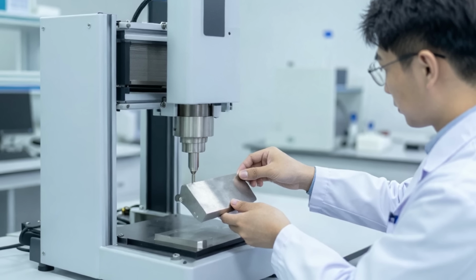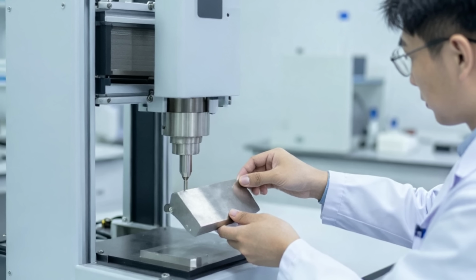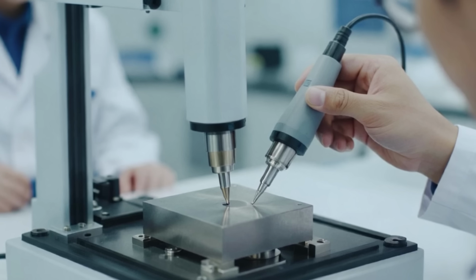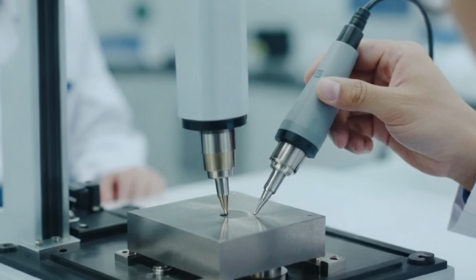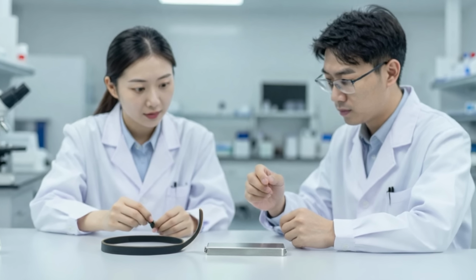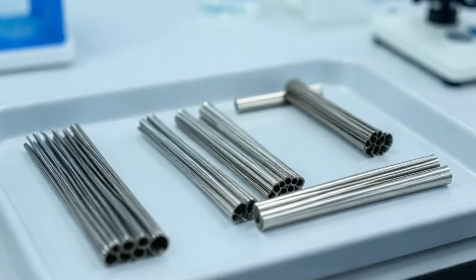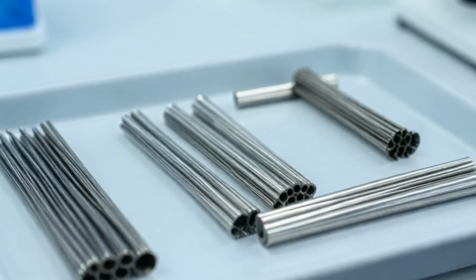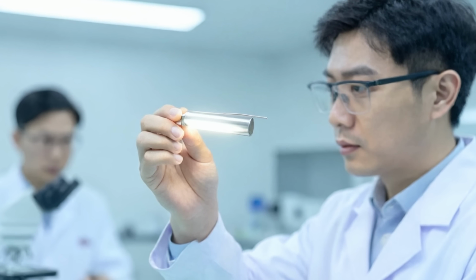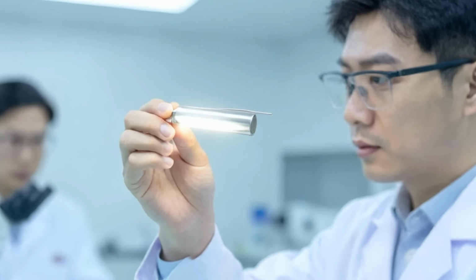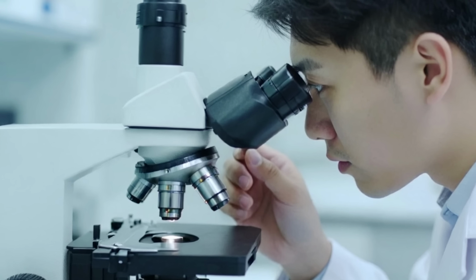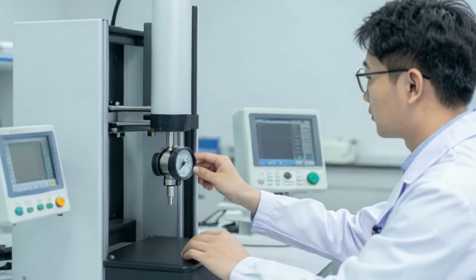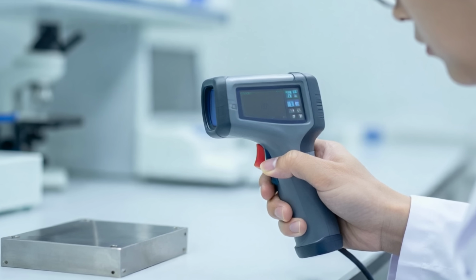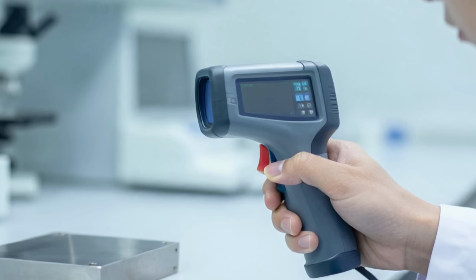Certain materials, when you mechanically stress them, release heat, and when you release the stress, they absorb heat from their surroundings. In a rubber band, the effect is barely noticeable. But in a class of metals called shape memory alloys, the effect is dramatic. The most studied of these alloys is nickel titanium, commonly known as nitinol. When you compress or stretch nitinol, its internal crystal structure undergoes a reversible phase change, shifting from one arrangement called austenite to another called martensite. That transition releases a measurable burst of heat. When you release the mechanical stress, the crystal structure snaps back and the material absorbs heat from whatever is around it, effectively cooling its surroundings.